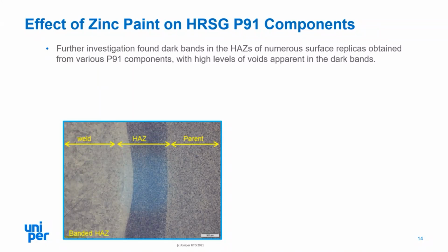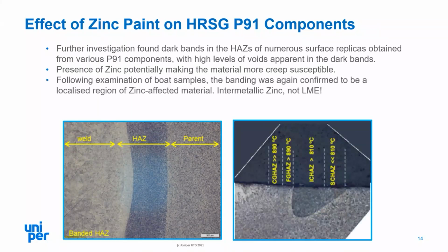What seemed to be apparent was that the presence of zinc in this dark band was making the material more susceptible to creep damage. Following examination of a boat sample, once again echoing comments that Jeff said about the value in taking boat samples where concerns are raised, the banding was again confirmed to be a localized region of zinc affected material, confirming the on-site observations. However, the zinc itself was seen to be intermetallic and not liquid metal embrittlement, as initial concerns raised.